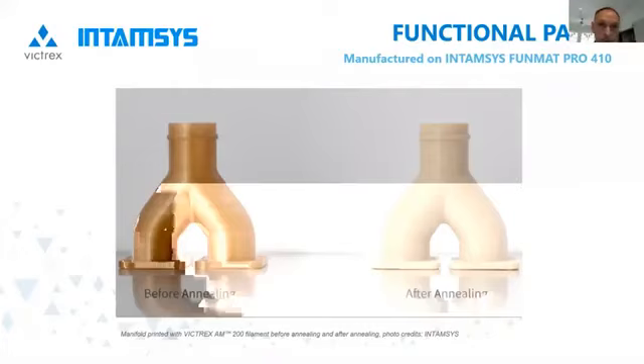Now, Victrex AM200 provides this flexibility for you to choose which method works best for your application and depending on the equipment that you've got. So you can print amorphous and leave it amorphous. You can print amorphous and post anneal it, or you can print directly crystalline with certain printers. So for example, if you're lucky enough to have the INTAMSYS Pro 610 HT, there's a 300-degree build chamber and bed in that machine.